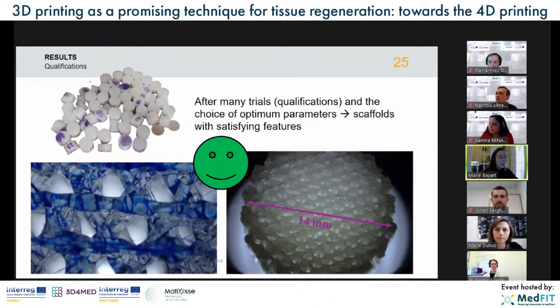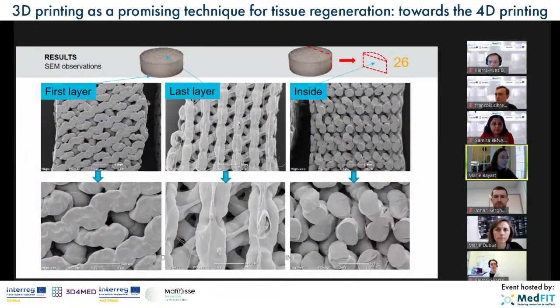And we made SEM observation, scanning electron microscopy observation. Here you can see that the first layer is not too flattened. It's a bit flattened, but we can see that we have porosity. The last layer is also satisfying. We've got straight rods. The pores are of good size. And also inside the scaffold, it's also porous. So we think that the exchanges will be good. And now Marie will talk about the biological result on this scaffold that she obtained.